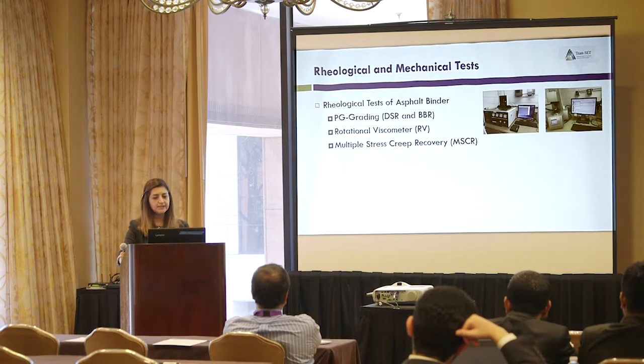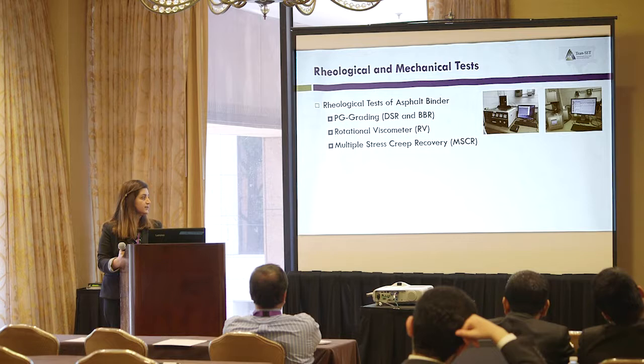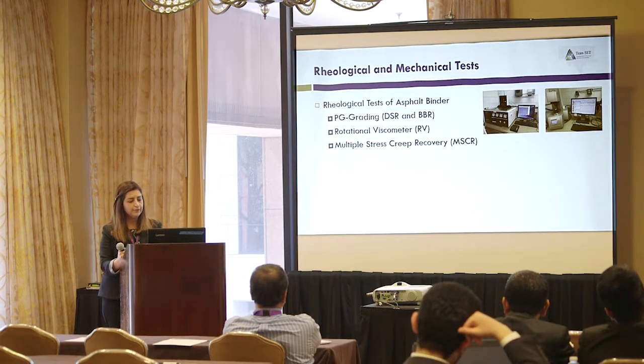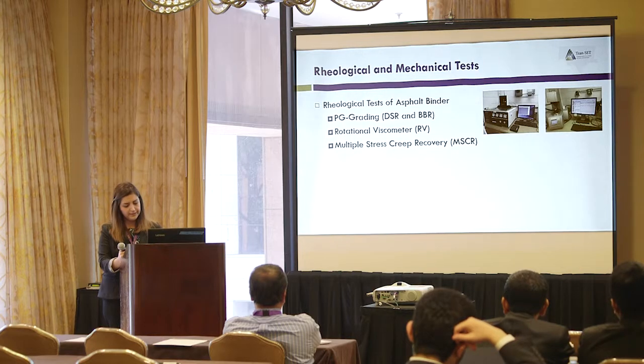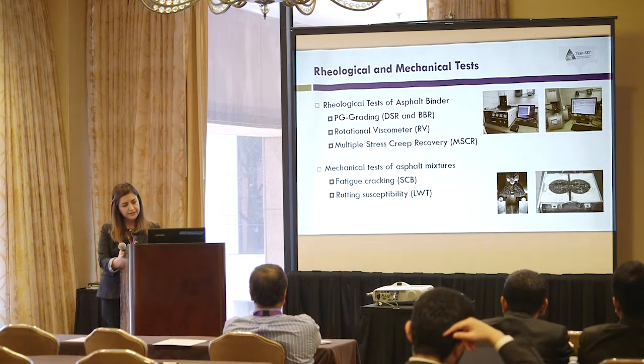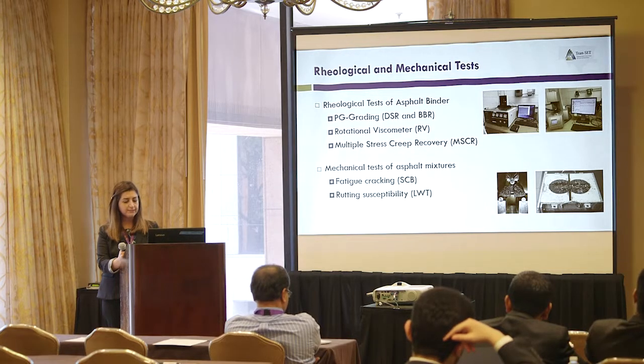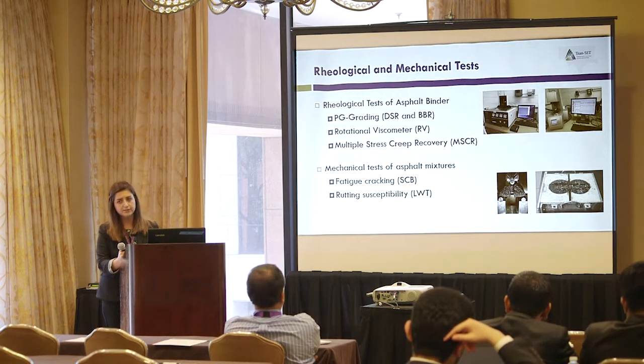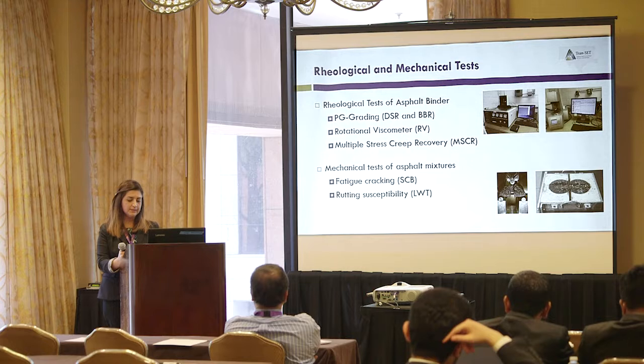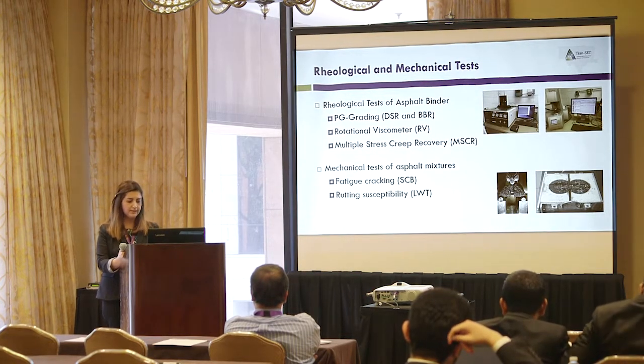For rheological tests, we performed rotational viscometer, dynamic shear rheometer, bending beam rheometer, and we performed multiple stress creep recovery. And for asphalt mixture tests, we did semicircular bending to measure fatigue cracking of the samples and loaded wheel tracking tests to measure the rutting resistance of different samples, with and without self-healing polymer and recycled materials.